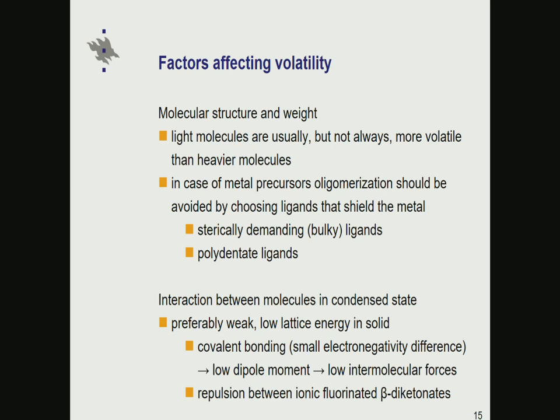Another thing, so this is molecular structure and weight. Another thing one should think about is how these molecules interact in the condensate. Preferably the interactions from one molecule to the other should be weak, because that means low lattice energy and easier volatilization. So one should find molecules where the bonding is quite covalent, so that there are only low dipole moments in the molecules, because if there are large dipoles, there is a lot of dipole-dipole interaction. These should be avoided, and if so, one has a better chance to make volatile precursors.